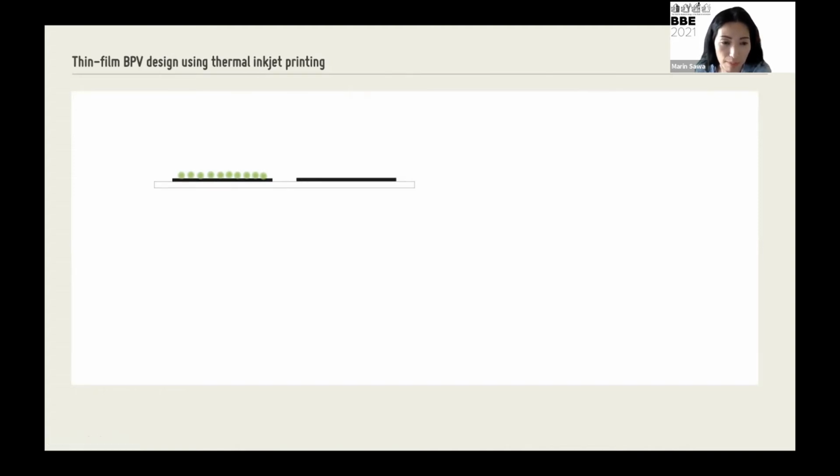The same inkjet method, which is actually thermal inkjet printing using heat to jet the materials from the nozzles, was applied to deposit carbon nanotube conductor, as well as the carbon-based catalyst for the cathode. And this really was the novelty of my inkjet method, allowing biological and non-living layers to be fabricated in a single process, but in different steps.